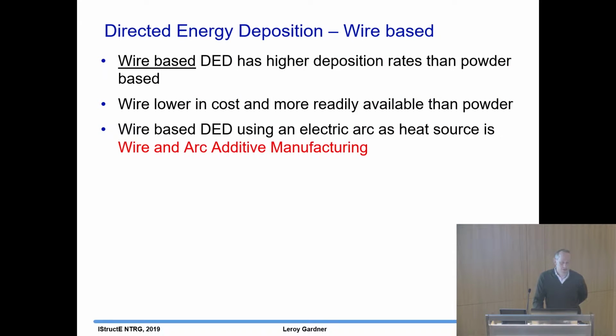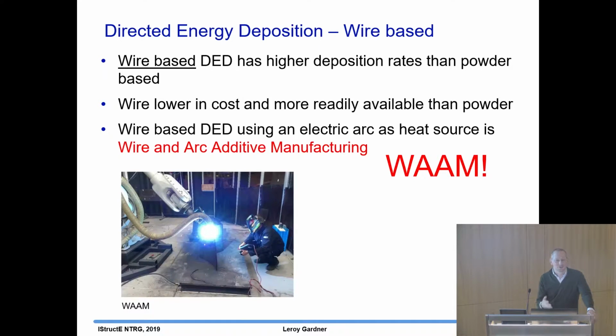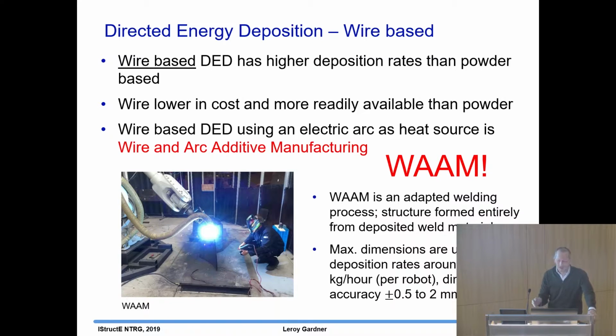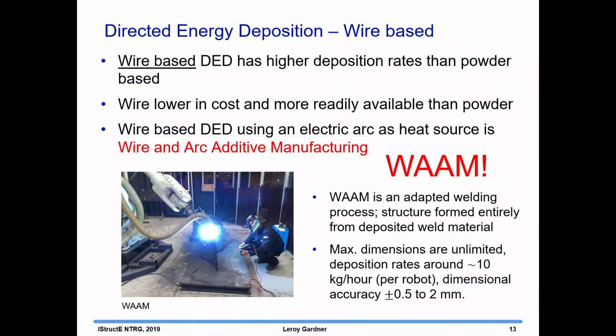Wire-based directed energy deposition, which uses an electric arc as the heat source, is called wire and arc additive manufacturing. This has by far the best acronym, WAAM. And this is the method that was used to create the bridge that I'm going to be talking about. It's essentially an adapted welding process. The structure is formed entirely from weld material. Maximum dimensions are essentially unlimited, and deposition rates of up to about 10 kilograms per hour per robot can be achieved. Dimensional accuracy is reasonable, and there's potential for this to improve with better control with time.